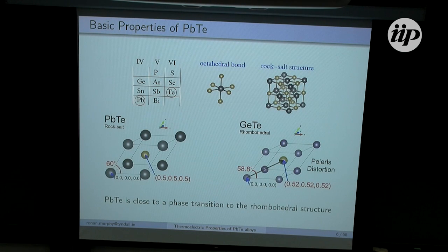So to start off with, I'll just mention a few basic properties about the proximity of lead telluride to this lattice instability. It's a group 4-6 material. The lead atom has 2 p valence electrons. The tellurium atom has 4 p valence electrons. These hybridize and are then shared among the octahedral bonds in the material. Ultimately, we see that it forms in the rock salt structure. Because of the nature of these bonds, the structure itself is rather weak and prone to distortions. In fact, it's energetically close to a phase transition to the rhombohedral structure. And I have here an example of a rhombohedral material, germanium telluride.